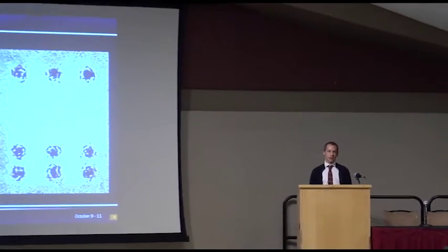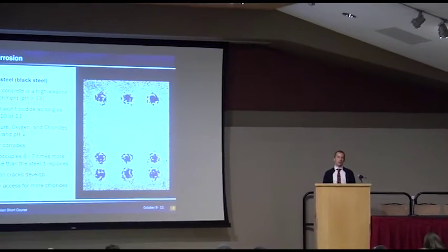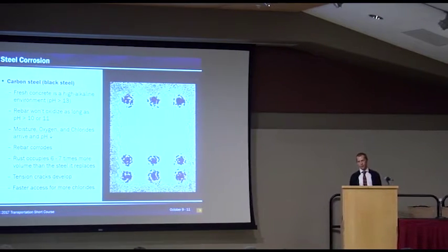So, steel corrosion. In fresh concrete, black steel, carbon steel, doesn't have any problems. Fresh concrete's a high alkaline material. pH's around 13, steel has no trouble. Steel's not going to have trouble unless the pH drops below probably 10 or 11. What happens is that water, air, and especially chlorides can get through that concrete. They can lower that pH, and once it does, steel does corrode.